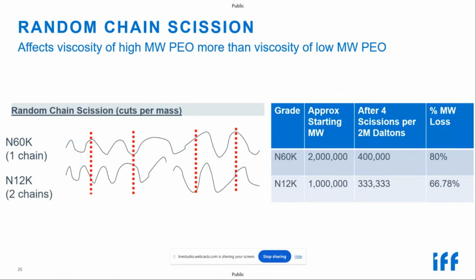The example I'm using to display this is N60K, which has a molecular weight of 2 million. It has 4 chain scissions, cutting it down to 5 chains of average molecular weight of 400,000 per chain. That's an 80% reduction in the molecular weight from a starting 2 million. In comparison, I'm showing N12K, which is approximately a 1 million molecular weight chain, but we have to do it on the same weight basis as the N60K. So 2 chains of N12K equal the same mass as the N60K. The same 4 cuts over 2 chains of N12K result in 1, 2, 3, 4, 5, 6 new chains with an average molecular weight of 330,000 daltons. That's a 66% loss in molecular weight.